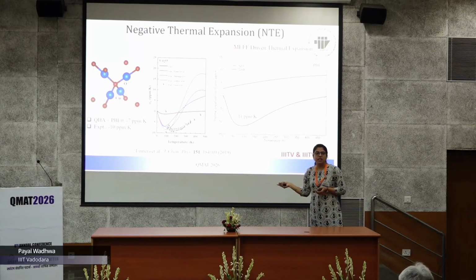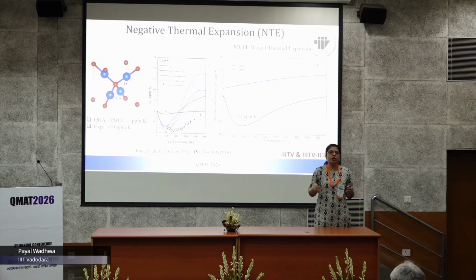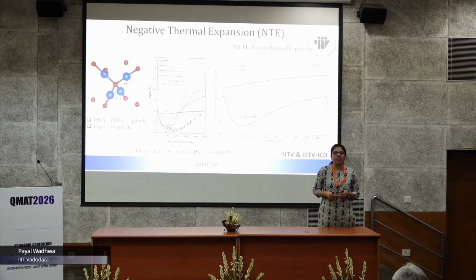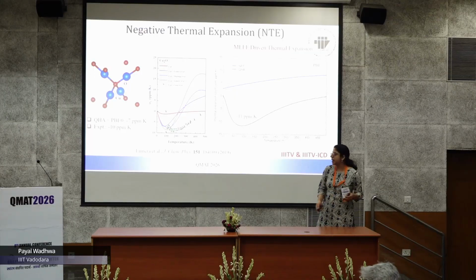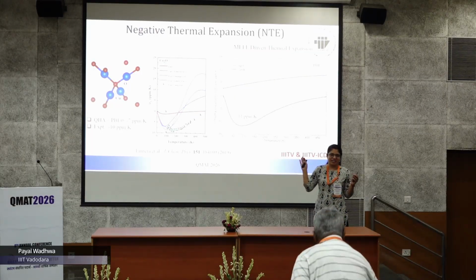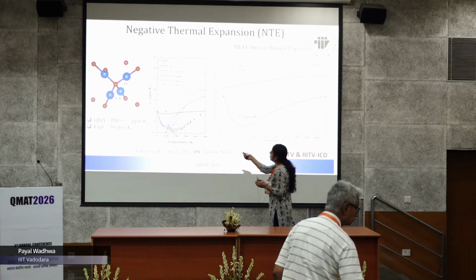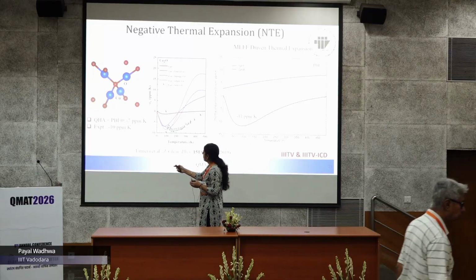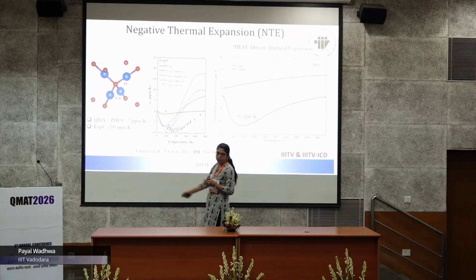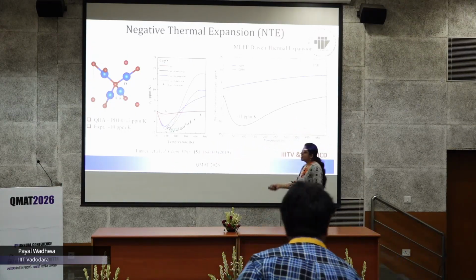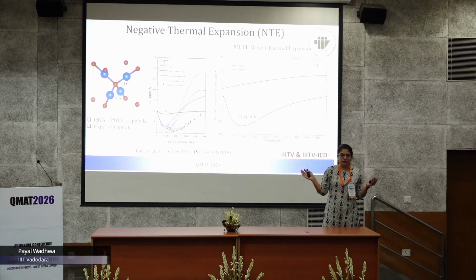In general, these thermal expansion calculations are done on a supercell. So you can imagine the computational cost of a supercell with 25% exchange, right? It would take months, right? But also the experimental values have shown this value as minus 10 ppm per Kelvin, parts per million. So again, here we train the force fields.